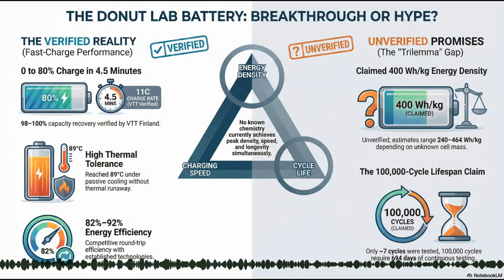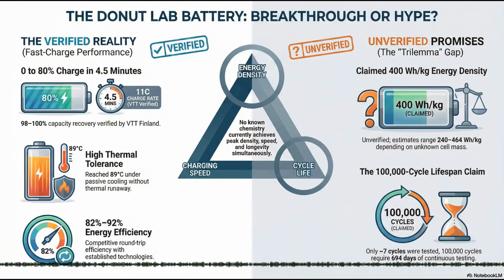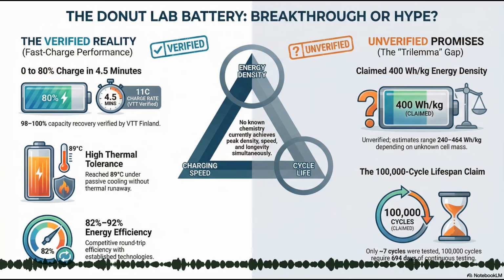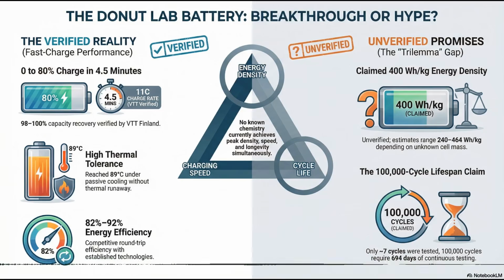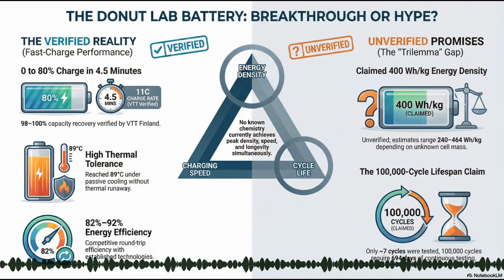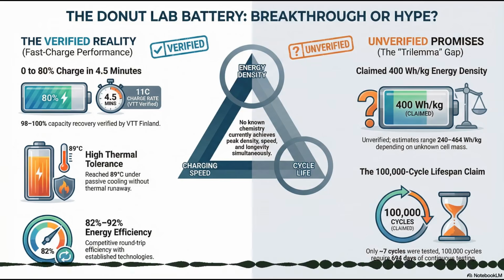Right. So then Donut Lab walks onto the stage at CES 2026 and essentially says, we choose all three. They announced a single cell with 400 watt-hours per kilogram, 11C charging, which is 0 to full in about 5 minutes, and the number that really broke the internet, 100,000 cycles. Which is just an extraordinary claim.